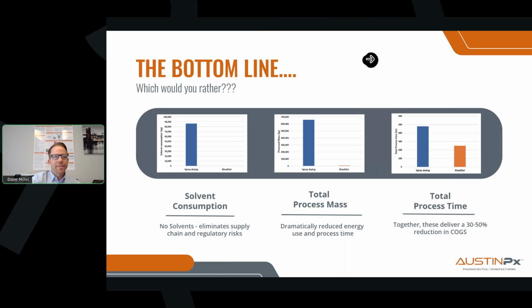So the bottom line, this slide really brings the message home. When you look at spray drying versus KinetiSol side by side, it's a really stark contrast. And the question is, which would you rather have? So on the left, looking at solvent consumption, not to beat this drum over and over again, but it takes tens of thousands of kilograms of solvent for spray drying, none for KinetiSol. And it just eliminates a lot of complexity and risk in terms of supply chain dependency and solvent handling issues, and the potential future risk of regulatory constraints on the use of solvents.